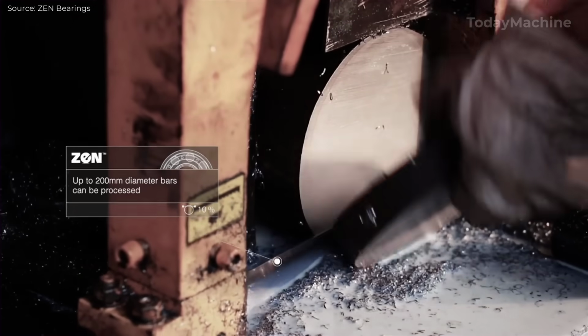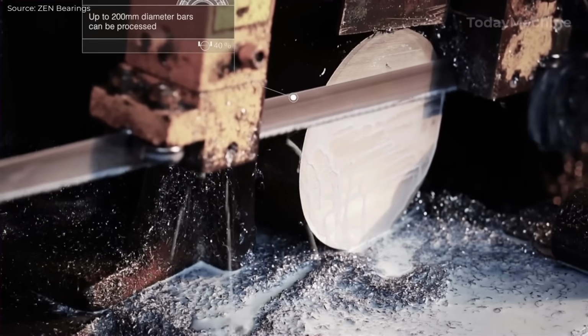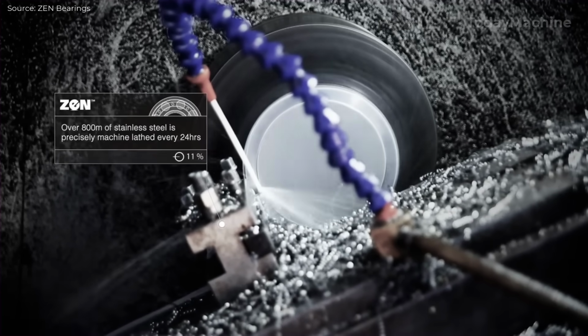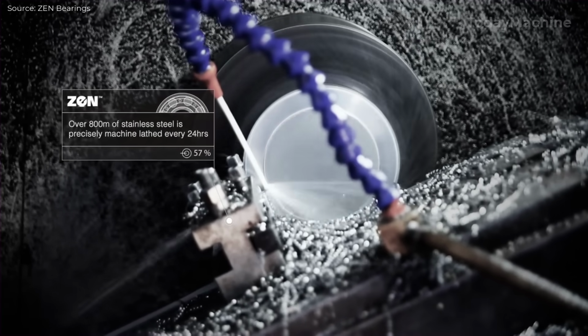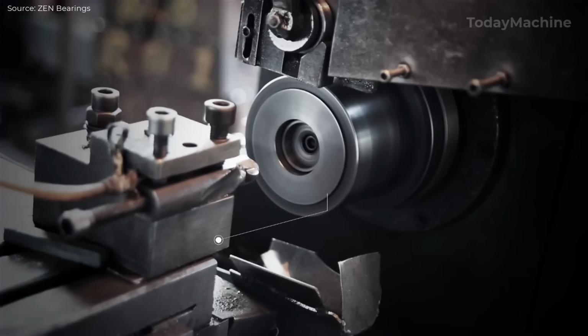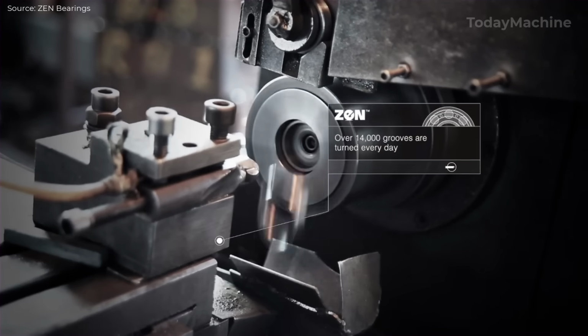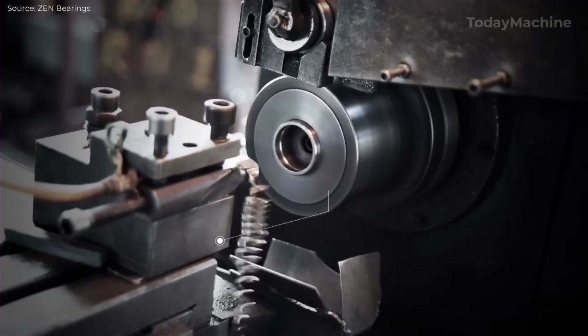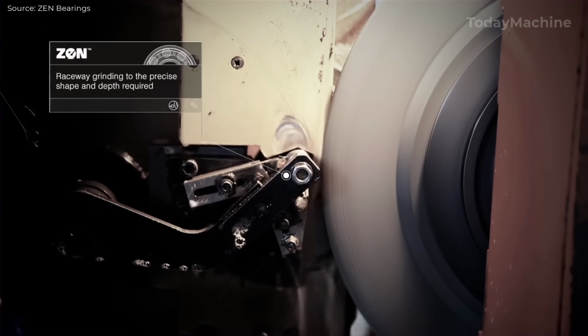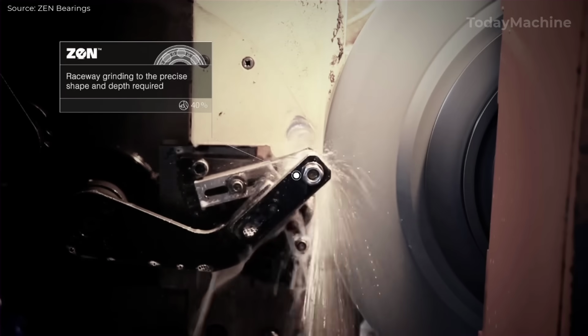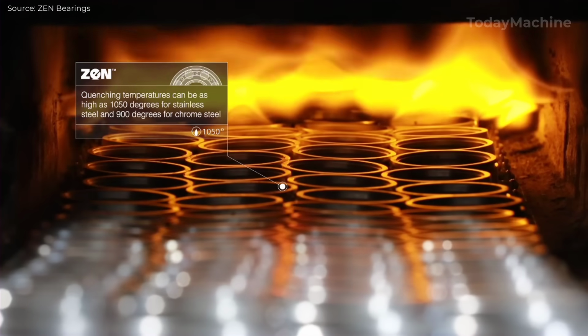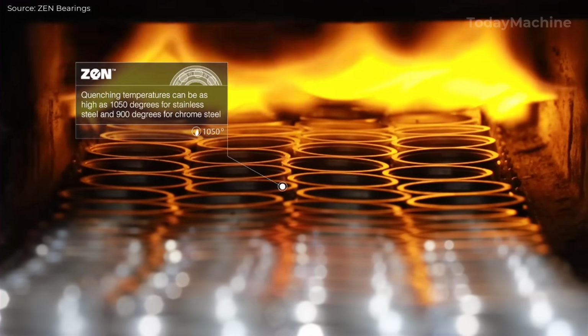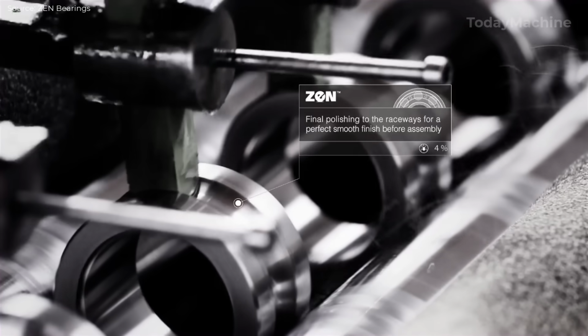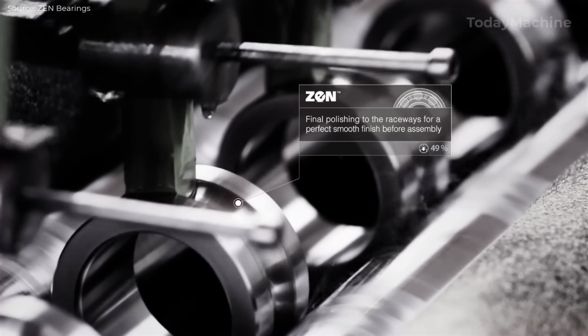The manufacturing process of bearings at Zen's factory begins with cutting steel rods, handling bars up to 200 millimeters in diameter. Each day, over 800 meters of stainless steel undergo precise lathe machining, creating more than 14,000 grooves. Following this, raceway grinding is conducted to achieve the exact shape and depth necessary for optimal bearing performance. The bearings are then subjected to quenching, with temperatures reaching up to 1050 degrees Celsius for stainless steel and 900 degrees for chrome steel, ensuring the material's hardness and durability. After heat treatment, the raceways are finely polished to achieve a smooth finish, critical for reducing friction during operation.